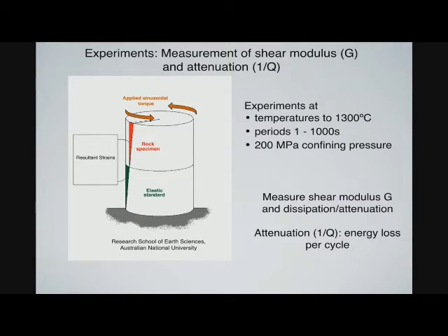Of course, we can't do that in the lab at high pressure and temperature. So instead of having a standing wave, we deform the sample. Instead of just compressing it like you did with a dead weight, you'd be torquing it, right? You'd be twisting it back and forth, and you do that periodically, and you simulate passing seismic waves. So we can do that at high temperatures.